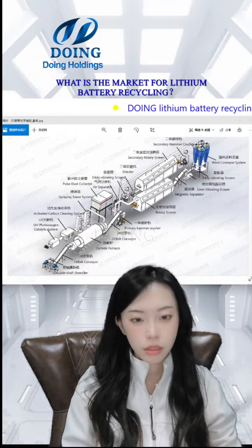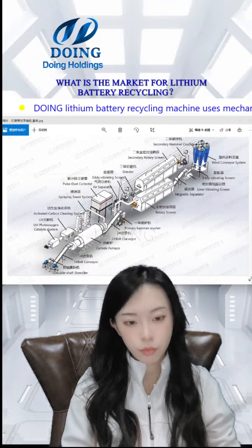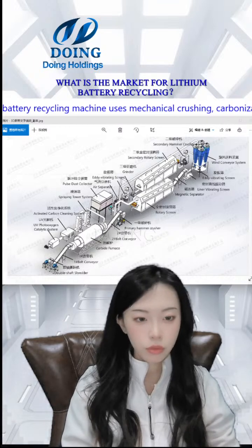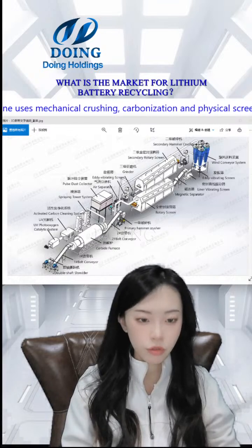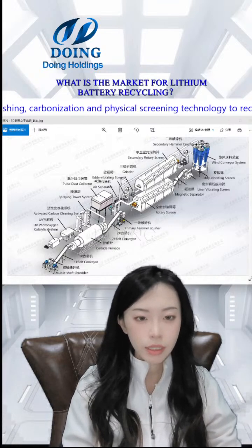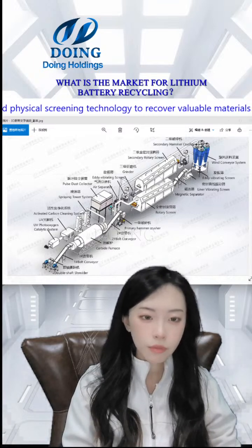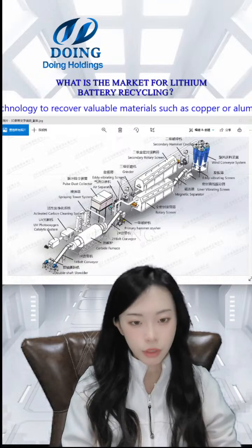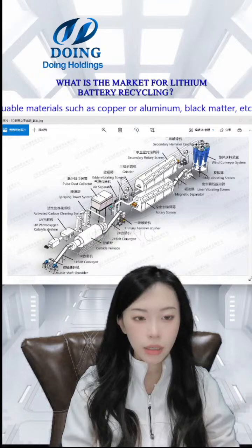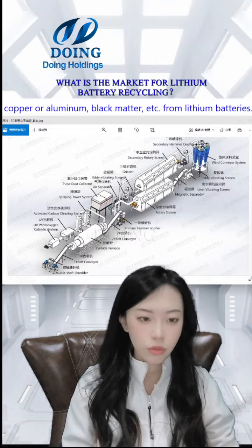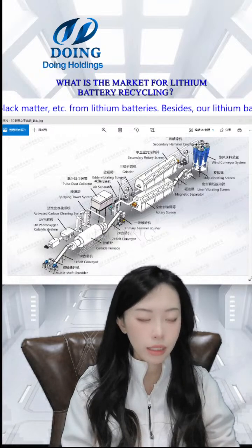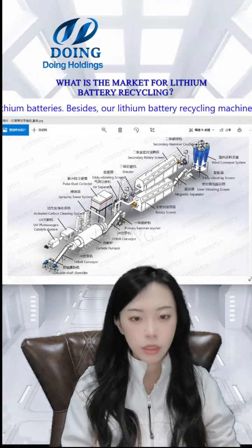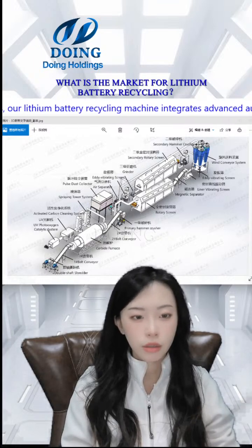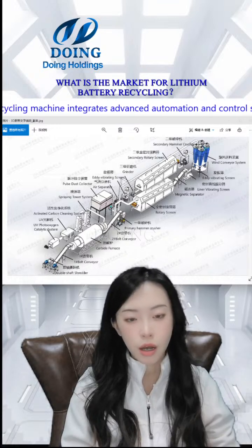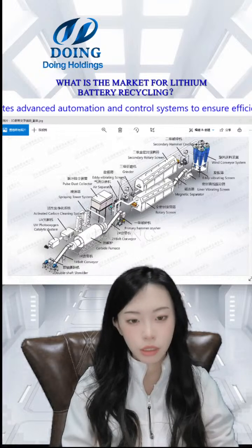And then the second is the belt conveyor to put the wet material into this double shaft shredder to shred it to 3 to 5 centimeters, and then it comes to the condensation furnace or the carbonization furnace. It will use electrostatic heating or gas heating. The temperature is 100 to 450 degrees, and the electrolyte of the battery will be volatilized for harmless treatment. It's better for machines of 500 kilograms or more.